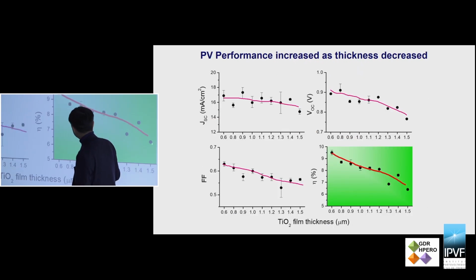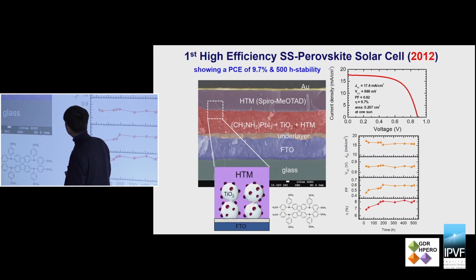And then we further decreased the thickness down to 0.6 micrometer, and saw a gradual increase up to 10% efficiency, which is due to the increased open circuit voltage and increased fill factor without a change in short circuit photocurrent density. So we actually published, we got 9.7% efficiency from this 0.6 micrometer titanium oxide film, and this is the first version.